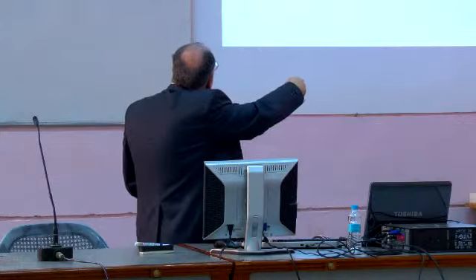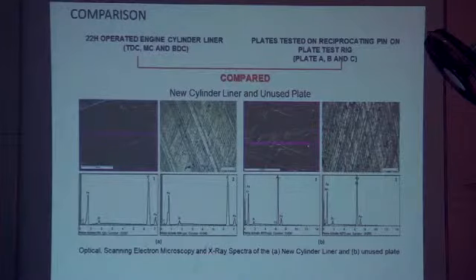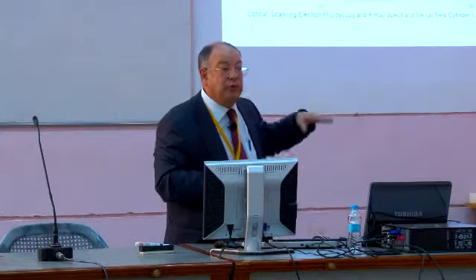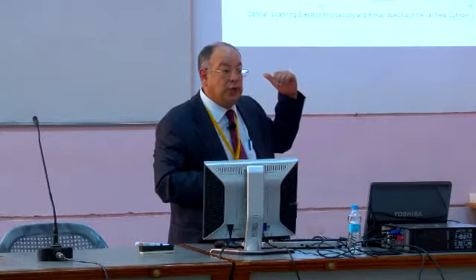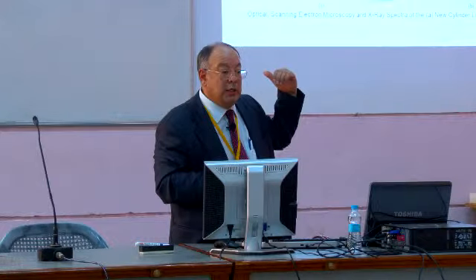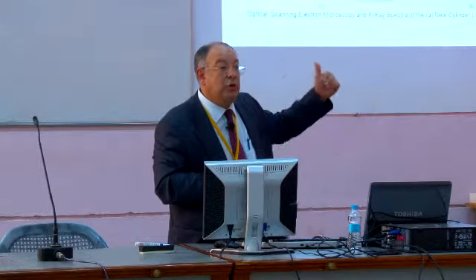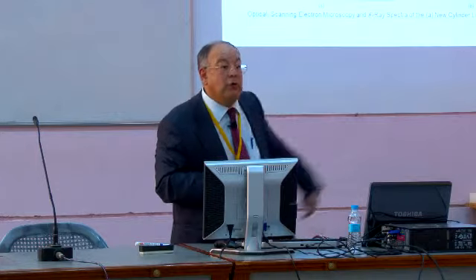I compared this with the engine and the pin-plate test rig. If you compare this one, you will see this is a new cylinder liner, and we use the plate, the same plate - even the same plate sometimes cut from the engine. If we couldn't cut it, we honed it under the same conditions. We measured the honing, we did honing measurements of the liner, and we honed the plate again.